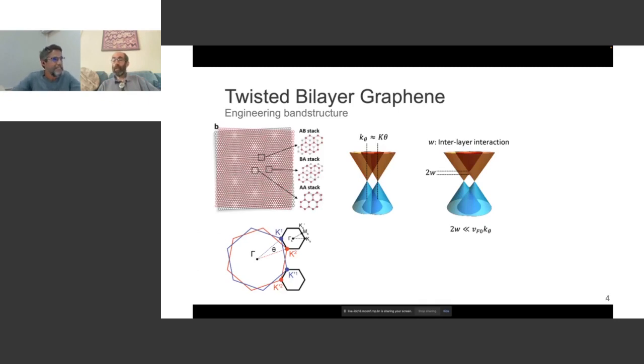So eventually this band structure should become flat, meaning energy is independent of momentum. And it turns out that one can predict what twist angle this should occur at, because it's known what size this gap should be. And so if you equate the size of that gap to the velocity of electrons in a single layer of graphene times the shift in momentum between the two layers due to the angle, then you can predict what angle this should occur at. And Bistritzer and MacDonald predicted that at about 1.1 degree twist angle, you should get this condition of a flat band.